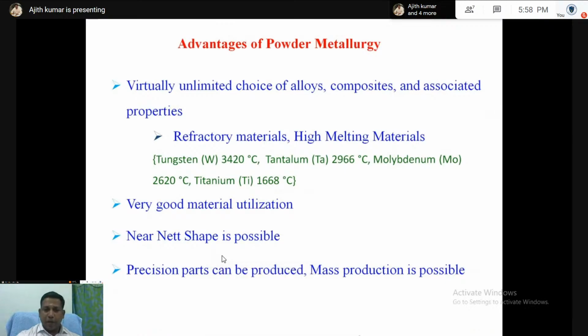In the case of metal casting, we can't do that with any metal. It's not possible because some refractory materials, high melting materials like tungsten, tantalum, molybdenum, titanium, have very high melting temperatures, about 3,420. So melting and casting is very difficult. For this kind of material, powder metallurgy is the best method to make a component or parts. Very good material utilization, near net shape is possible. Precision parts can be produced. Mass production is also possible in powder metallurgy.